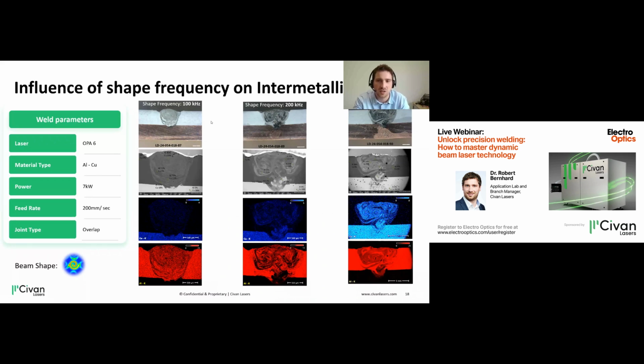So intermetallic mixing here means we are doing different shape frequencies in order to get the intermetallic mixing of the top material in overlap configurations just right with the bottom material. So in this case, we have aluminum to copper welding, 7 kilowatts, 200 millimeters per second in the overlap configuration. And here we are using a beam shape that's kind of a spiral. And this spiral now changes how fast the spiral is generated electro-optically. And what we can see in the results is that the shape frequency has a very big impact on how the mixing works.